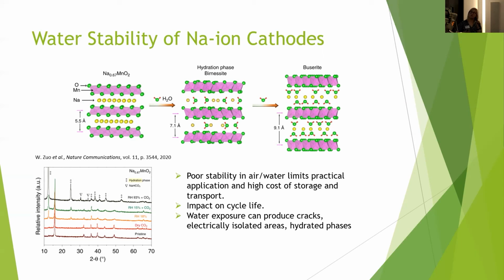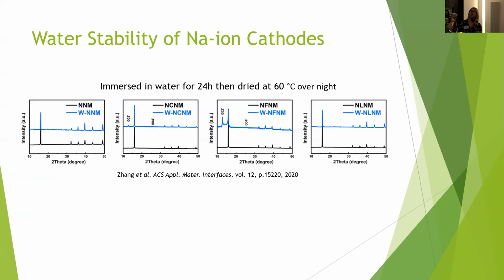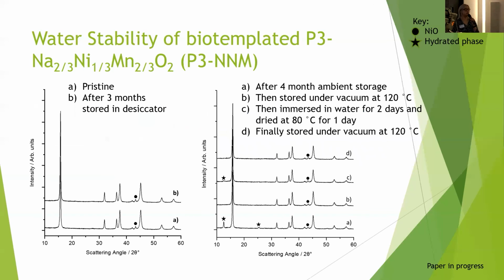However, different things can affect water stability. And one thing is the different elements that you put into your cathode material. So we can see the structure on the left-hand side is sodium, nickel, manganese. After immersion in water, there are no additional phases formed. So it's really stable in water. But then you can see these additional peaks form after immersion. And this is with the addition of cobalt and iron. So that negatively impacts the water stability. So they might not necessarily be a good candidate for using water-based binders. But the structure I'm looking at, I found that it is relatively stable in water.